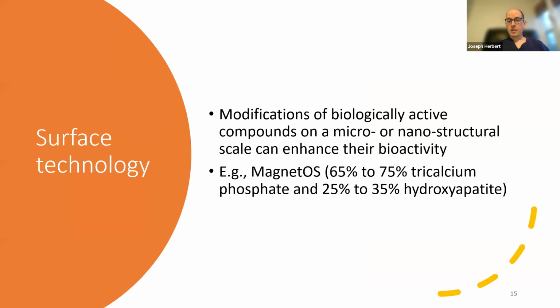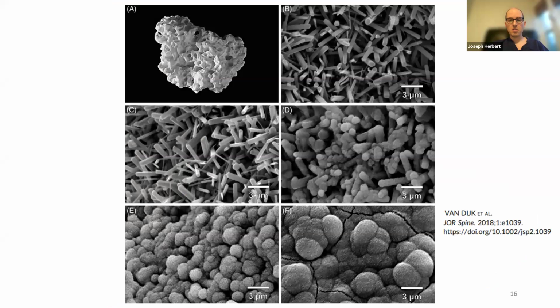And then you can also take biologically active compounds. So we talked about PEEK and titanium, which are biologically inactive, but you can also take biologically active compounds and then modify them on a micro or nanostructural level to increase their bioactivity. The example that the residents at University of Washington will probably see the most of is MagnetOS, just because that's used quite a bit at Harborview. This is a compound that's 65 to 75% tricalcium phosphate and 25 to 35% hydroxyapatite. The key feature, and where they get their intellectual property, what the company claims makes it unique, is this nanoscale microstructure. It's got these very rough glass crystal-like structures, and this degrades over time as it spends time in the body.